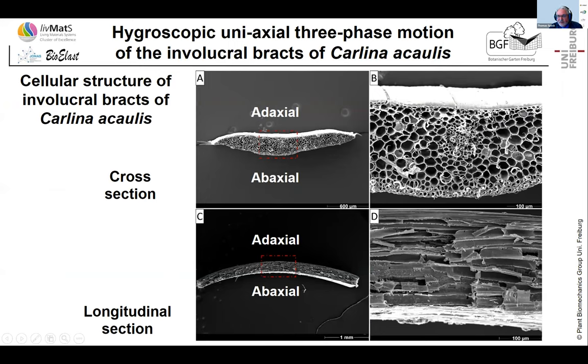You have layers which are totally different. You have a totally blocking layer at top where no water can go through. You have easily accessible layers at the base where water is more or less sucked in. And you have different layers in the center which are delaying water access. So you have three types of layers: blocking layers, restrictive layers, which allow water but with a time delay, and actuating layers which allow immediate water access.